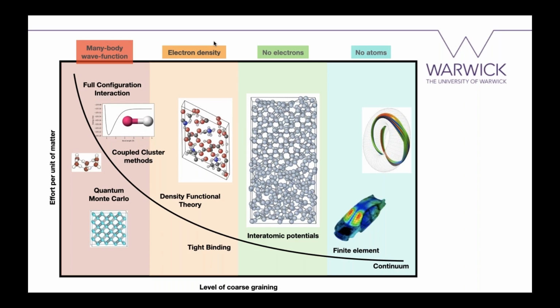As you go from the left to the right, your effort also changes. You can only do a few electrons with the full configuration interaction method, and then as you increase your level of coarse graining, you can go to bigger and larger systems for longer simulation times. So there's this hierarchy of methods. Sometimes we have the problem that as the accuracy goes down with the level of coarse graining, our simulations become less predictive. There is this huge change in accuracy when we coarse grain out the electrons.